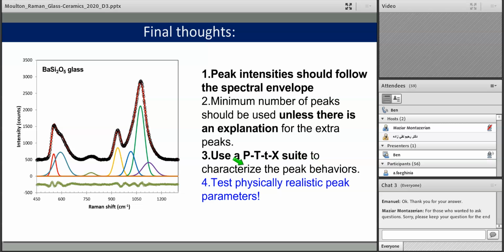And even if you don't get an absolute model, you can still characterize the relative behavior of the peaks based on your other variables. I would highly recommend in the case of silicates to look through the work of Nesbitt because we're starting to realize that these stretching modes in particular related to the Qn bands have very small ranges. They can't just be anything. You can't have a band of 100 with a width of 100 wave numbers and call it something that we see in crystals.